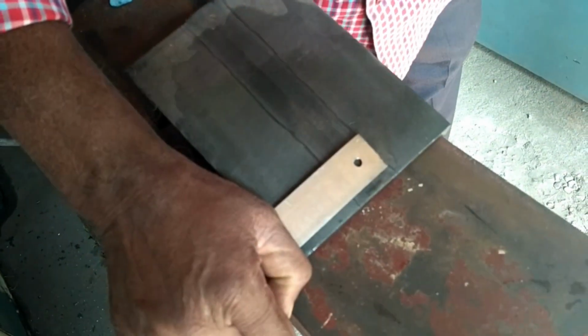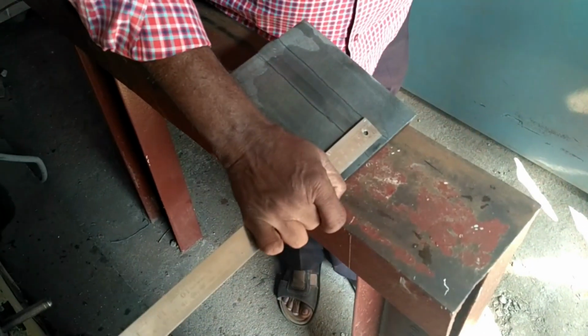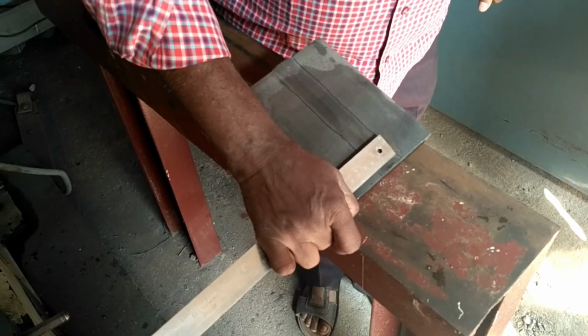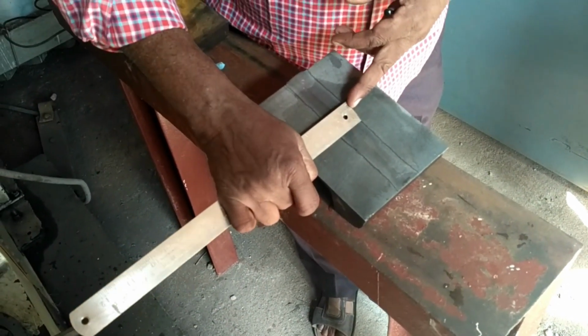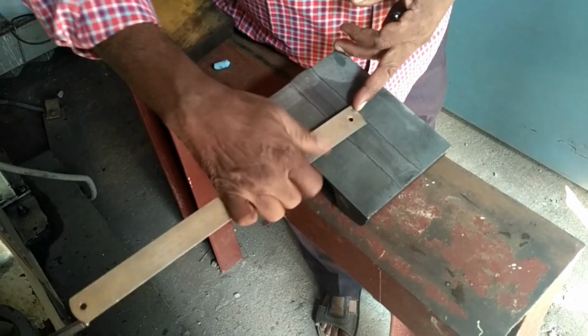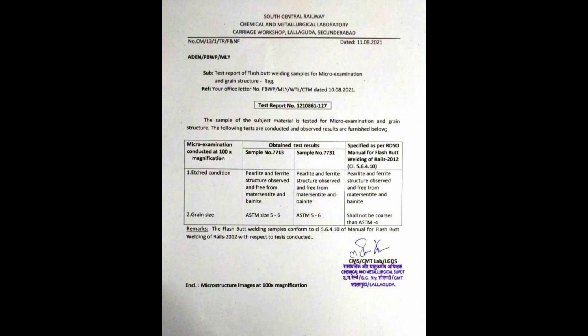Then the microstructure shall be free from martensite and bainite, and grain size shall not be coarser than ASTM 4 at 100x magnification. These reports are also kept here. The report from CMT, Lalaguda, says it is free from martensite and bainite. So that means that is a good weld only. And the microstructure with 100x magnification is also shown here.